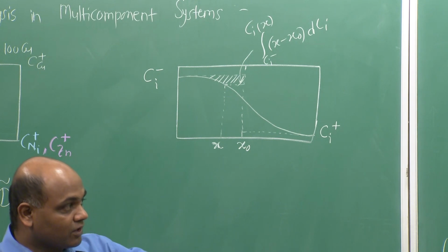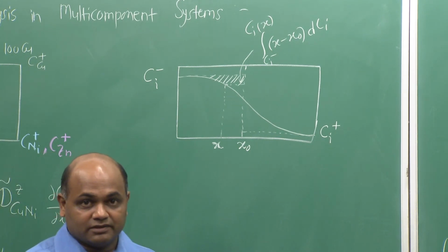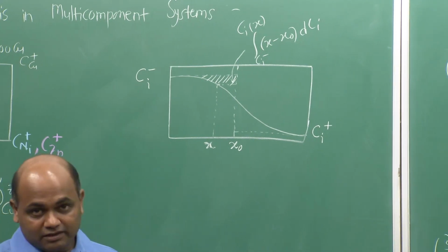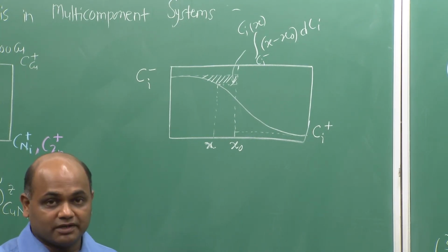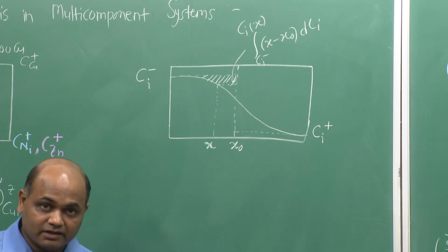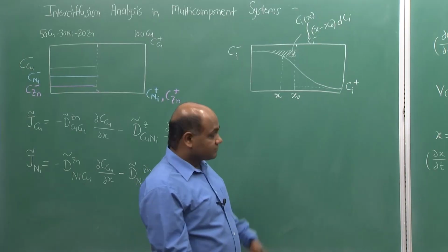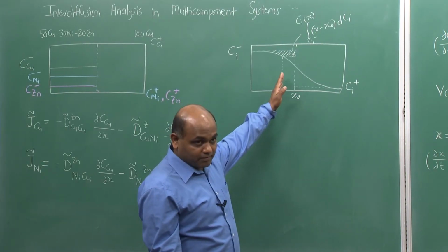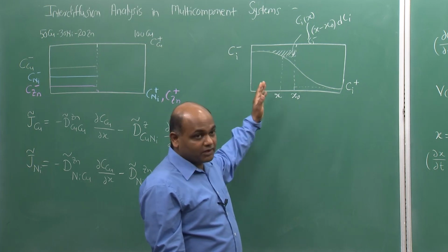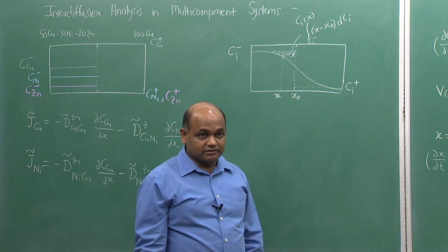We derived this formula again independent of the number of components, so this should be applicable to a multi-component diffusion couple. This way, we can obtain the interdiffusion flux of each component at every composition plane that is developed within the diffusion zone here.